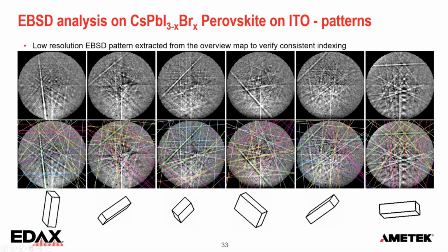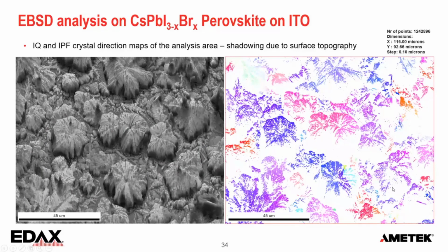If I get consistently the same lattice plane indexing that particular band, then I could optimize the reflector list and get good indexing everywhere. And that gave me this mapping result. So as you can see, on the left is the IQ map. And all those clusters of points index reasonably well. It's a topographic sample, so a lot of areas are just shadowed. So we don't get 100% indexing, but we get a lot of information from those different clusters.